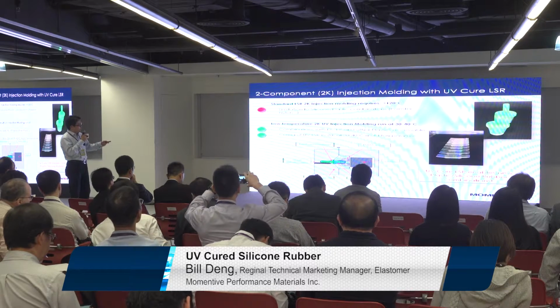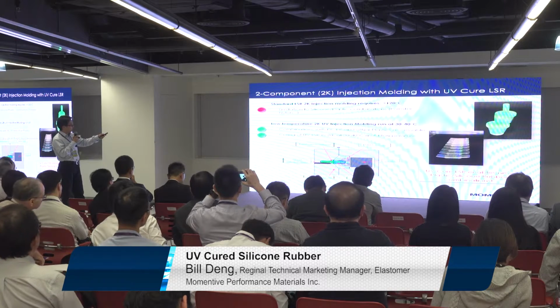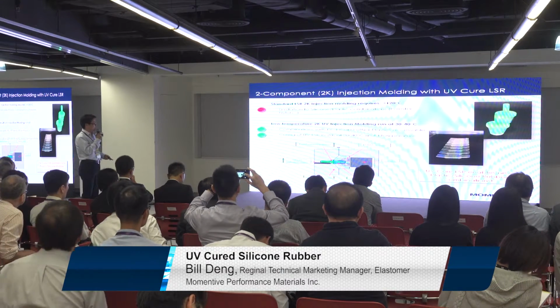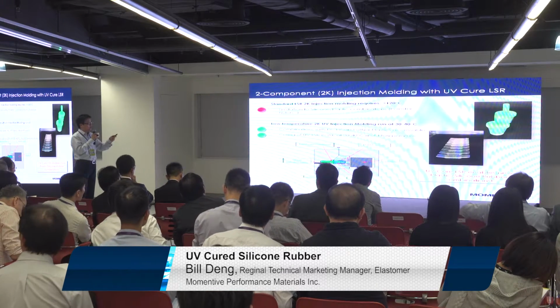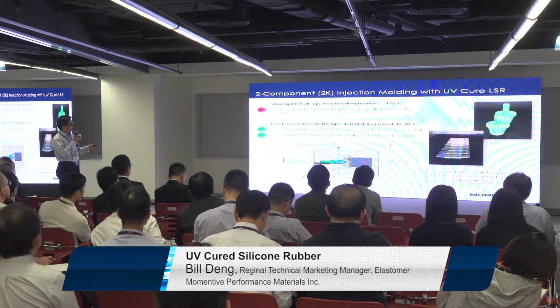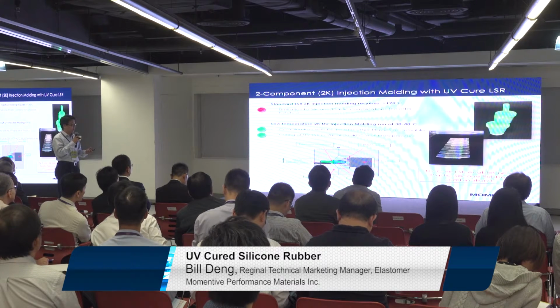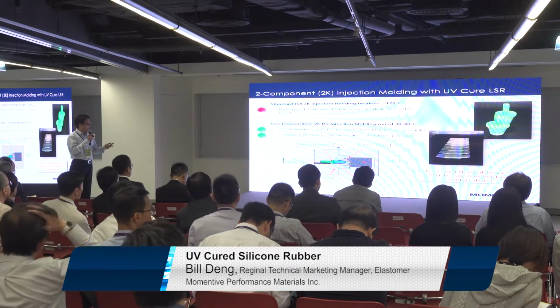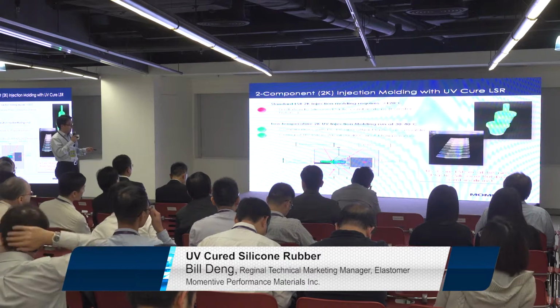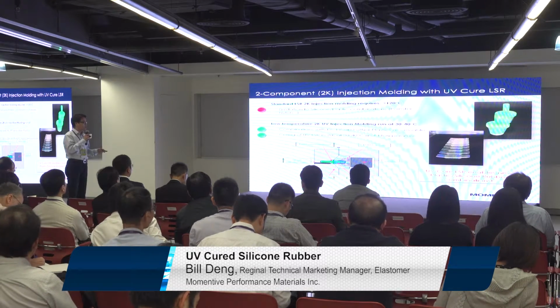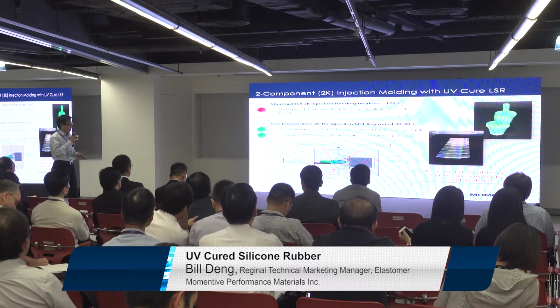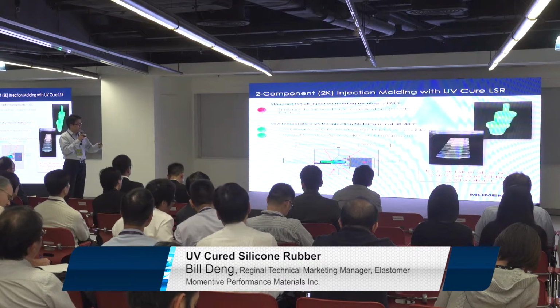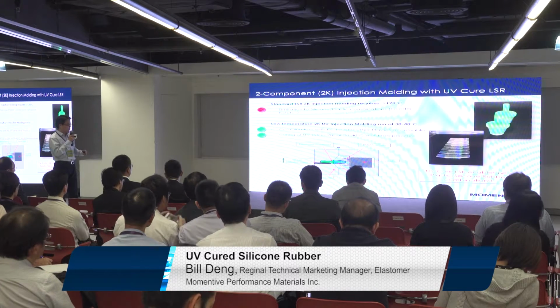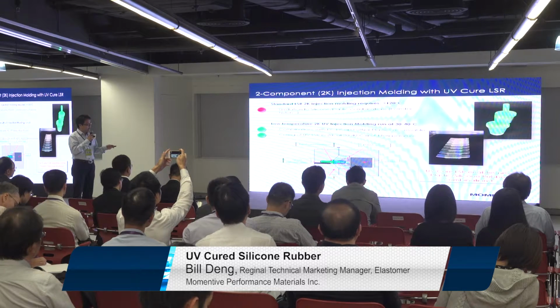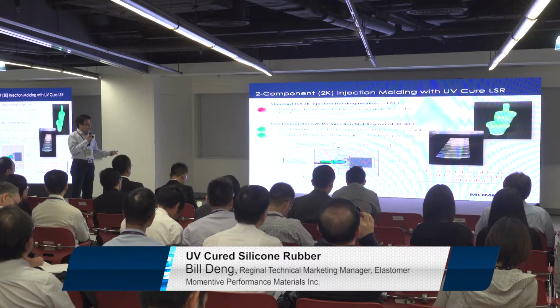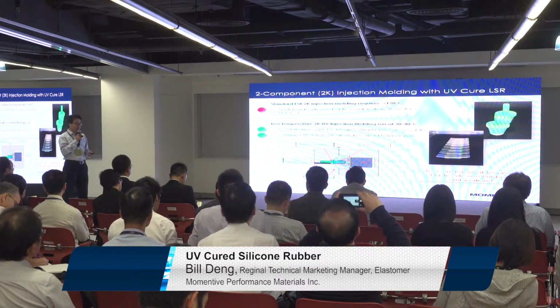So if we look at the comparison, we can see a traditional LSR 2K. 2K means two-component injection overmolding, which requires more than 120 degrees. It is a limitation to the silicone and plastic combination, especially for PP, as I mentioned, and polyester. For the low temperature UV cured process, we can run the overmolding at only about 30 to 40 degrees, which is room temperature. So it's very good for combining silicone rubber with PE, PP, and other plastics that have a very low melting point. And even though the temperature is lower, as I mentioned before, the curing speed is still very fast. That's why we can make even bigger or more complex parts.